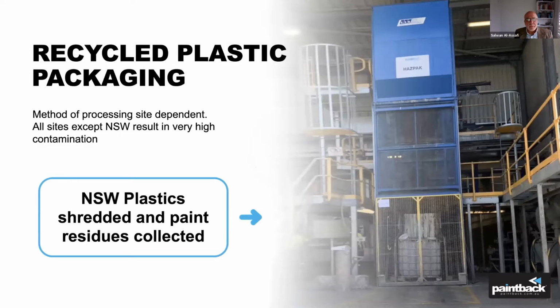In terms of how that works, for different states we have different processes. The main volume is coming from the large states like New South Wales, Victoria, and Queensland. These three states, we get large volumes from them. In New South Wales, we have an automated system called HAZPAK, so it's for mass production. They put in a large volume of pails, and all these pails get shredded. Liquid paint goes one side and plastic goes to the other side. The plastic gets taken out of this machine, and then it goes to washing and further processing, while paint goes somewhere else where we can deal with it, depending on what the end application is for it.